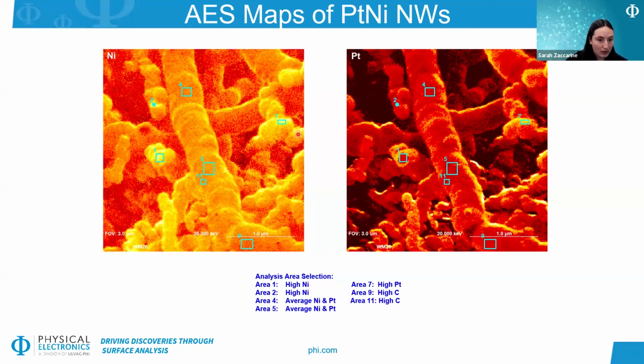So this is one example of a nickel map on the left, platinum map on the right, where we are analyzing numerous different areas and looking generally at the composition here. And we do see that there are some differences. So in these two areas, which appear slightly brighter on the nickel map compared to these other wire areas, we do see that there is a higher nickel amount in those areas.